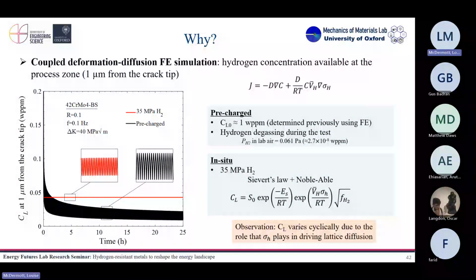To understand why, I couldn't find an explanation until we did some simulations. Basically, we wanted to know the amount of hydrogen that you have at the front of the crack when you are doing fatigue. So basically, how much hydrogen is being involved in this fracture process, in the cracking process, between the two methods. So what we see is the hydrogen content at 1 micron from the crack tip. And this is the time of the experiment, which really didn't matter for us. We just wanted to know what was happening. And see that we introduced a cyclic load for the two different conditions.